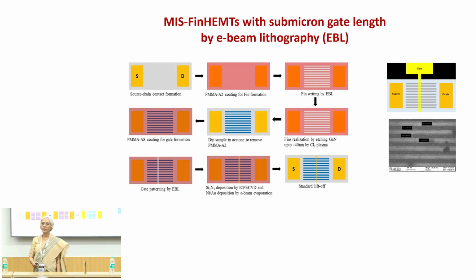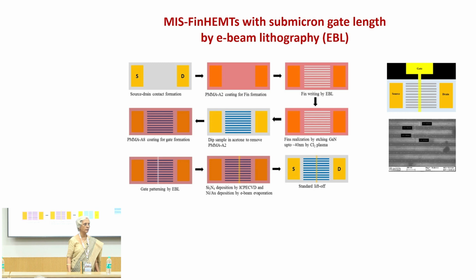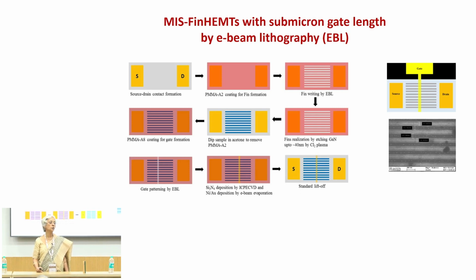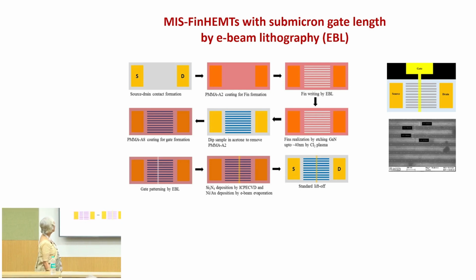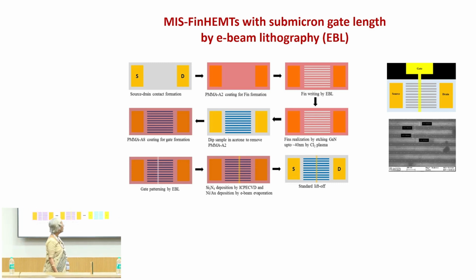Obviously, then in a fin HEMT, the control of gate over the channel is going to be much better, and we saw that when we fabricated both MIS HEMT and MIS fin HEMT with the same or similar gate length, we found that the MIS HEMTs show a lot of short channel effects, whereas a MIS fin HEMT shows almost ideal IV characteristics. So, this is the MIS fin HEMT fabrication with submicron gate length. As you can see here, in the region between the source and drain, we have the fins, multiple fins, and that fin is written by EBL. And you can see here the SEM picture, it is of the order of 200 to 225 nanometer fin width.